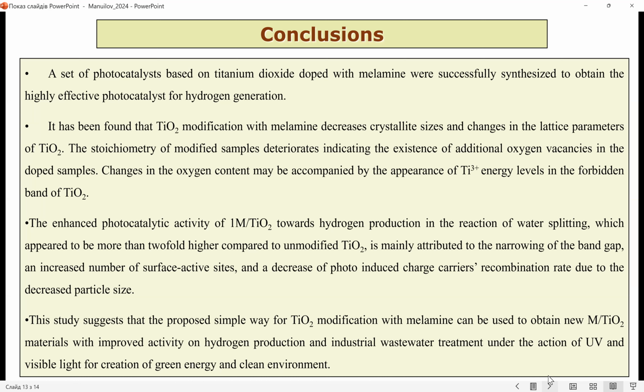We have some conclusions. A set of photocatalysts based on titanium dioxide doped with melamine was successfully synthesized to obtain a highly effective photocatalyst for hydrogen generation. It has been found that titanium dioxide modification with melamine decreases crystallite size and changes the lattice parameters of titanium dioxide. The stoichiometry of modified samples deteriorates, indicating the existence of additional oxygen vacancies in the doped samples. Changes in the oxygen content may be accompanied by the appearance of titanium 3+ energy levels in the forbidden band of titanium dioxide.